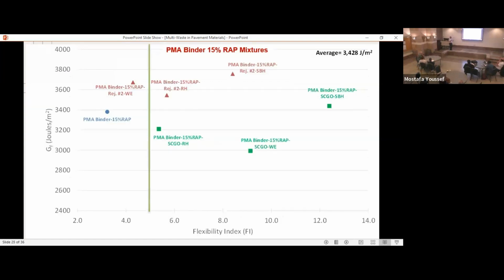Now let's change the binder to polymer modified binder. In fact, the binder itself, to begin with, would have failed in this test. If this was a standard, you wouldn't have accepted this mix to begin with, because its flexibility index is way down here. However, you combine it with this combination of ash and food waste oil, and you have pushed it really far into the flexible region, which everybody would love to see, only by playing with the binder.